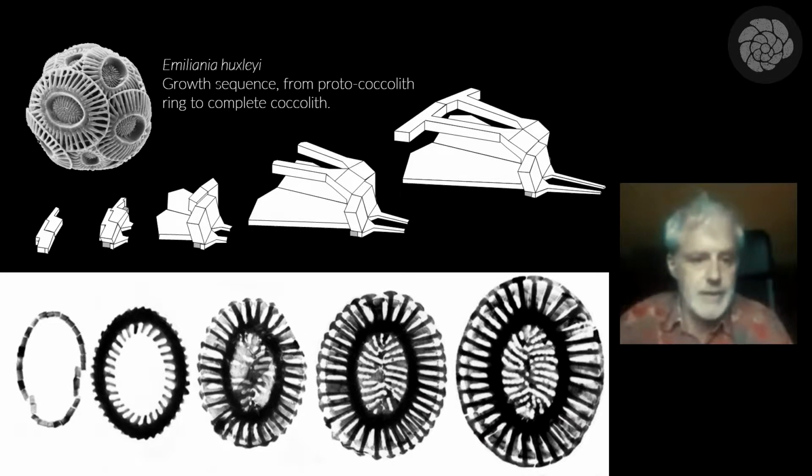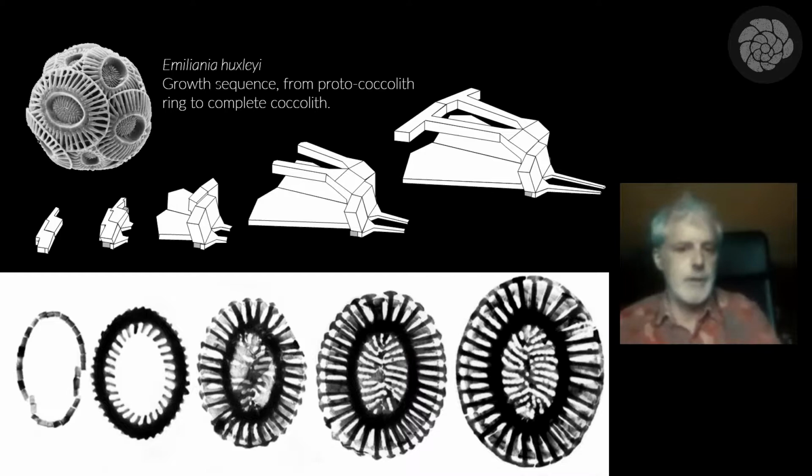It's one of the advantages of getting a growth sequence, so you can really start working out how the structure works. You can see very rapidly that it started as very simple crystals, but as they grow, they start kinking and overlapping with each other, and so the structure actually locks together. One consequence is that the nucleation phase determines exactly the number of crystals in the final coccolith, as there's no subsequent nucleation, but also it determines the crystallographic orientation, because they don't rotate or change orientation afterwards. Basically, they're nucleated in one orientation, and that orientation will stay as they grow and get larger.